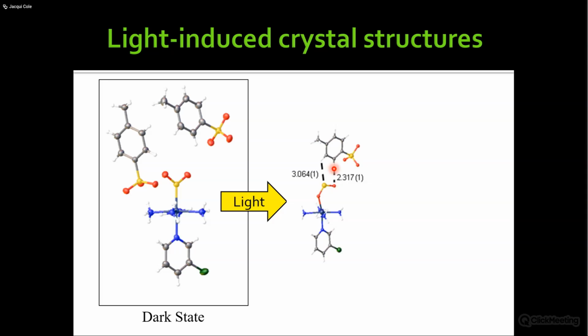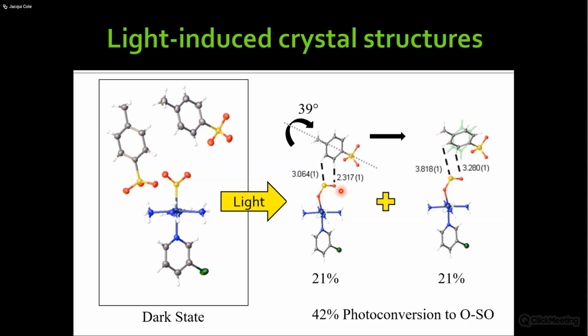interaction. It's really quite small, and so in fact it's so small that what happens is, not for all of the molecules involved, or the ions, but for most of them, the counter ion, the tosylate, actually rotates in terms of the arene ring. And what you can see here is then that the arene ring rotates sterically to alleviate that strain. So instead of 2.3 Angstroms, the separation of the hydrogen and this oxygen, you're now just over 3 Angstroms. So it's now a lot more comfortable.